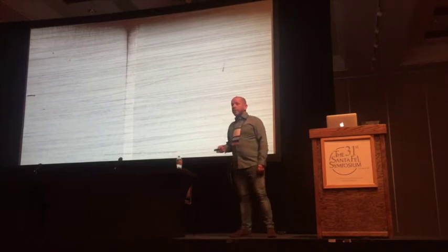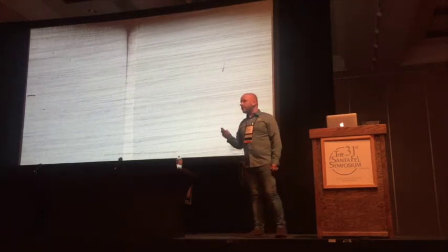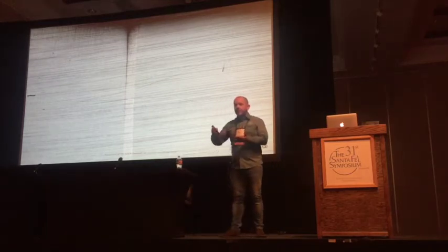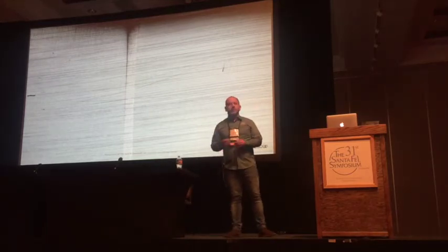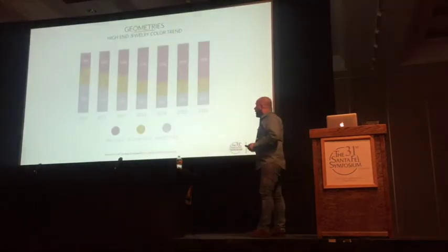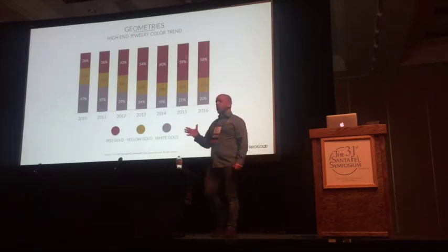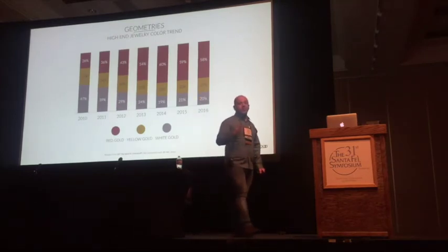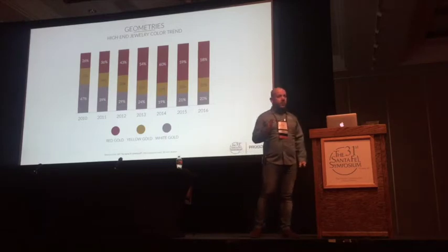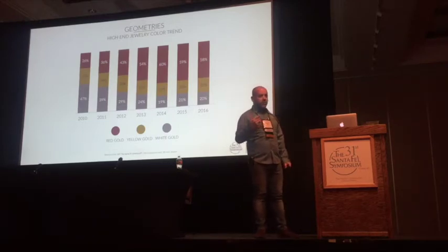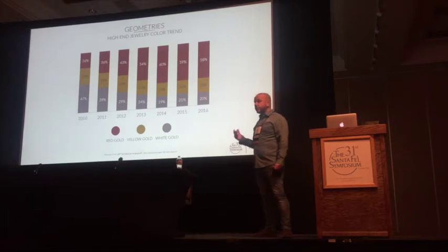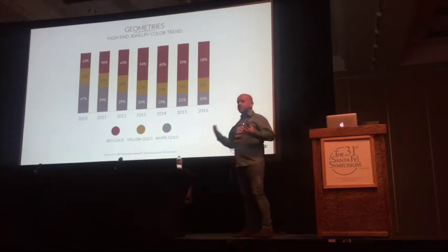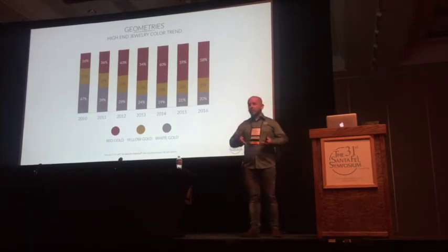Here we have an example of a white gold soldering line where, even when you are able to match the color, there is always something like a depression on the soldering, because the abrasion is different during the grinding and polishing process. And then, most of you know that rose gold is one of the most difficult colors to match with solders, except if you use laser. But laser is not really able to do a deep soldering.